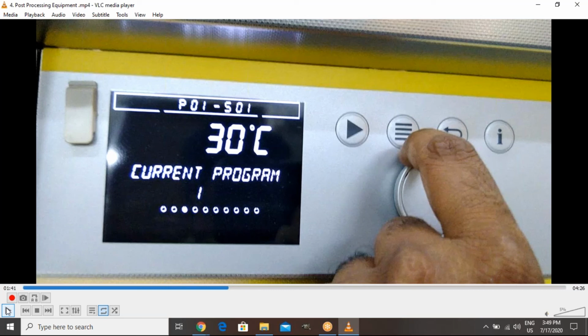The holding time for each and every material is different. It's not the same for all materials. Let's say for stainless steel, the 17-4 precipitation hardenable material we are using at NIT Warangal, the holding time is 1 hour at 480 degrees centigrade. So heating will continue until 480 degrees centigrade and will hold for 1 hour. After that, we'll go for furnace cooling.